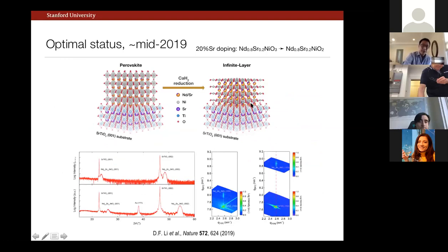this epitaxial relationship between the infinite layer structure and the substrate. And you can nicely see this by X-ray diffraction, right? You can see, for example, the perovskite peaks shifting out to higher 2 theta values corresponding to the reduction of the C-axis lattice parameter. And in all of the things I'm going to discuss here, the in-plane lattice parameters, excuse me, that can be observed by reciprocal space mapping are locked into the substrate. Okay, so we're always in a regime where the substrate dictates the in-plane lattice parameters.